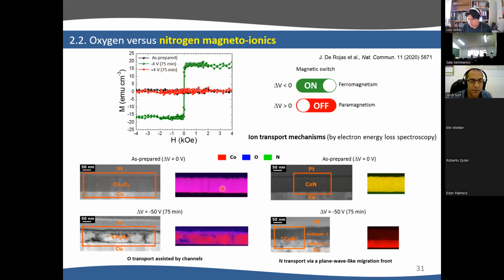Here are the yields from before, from the previous slides, and here are the yields for cobalt nitride, and it's a bit different. For cobalt oxide, there is this enrichment in cobalt or oxygen a little bit in random regions, but for cobalt nitride, the nitrogen seems to be removed layer by layer, and when you apply voltage, you form this kind of bilayer.